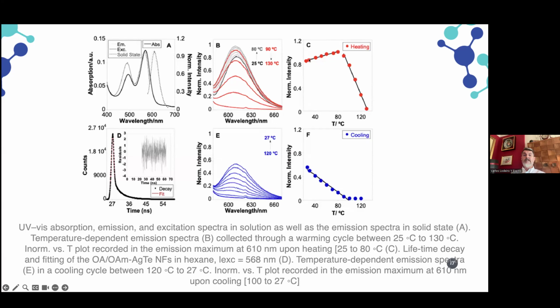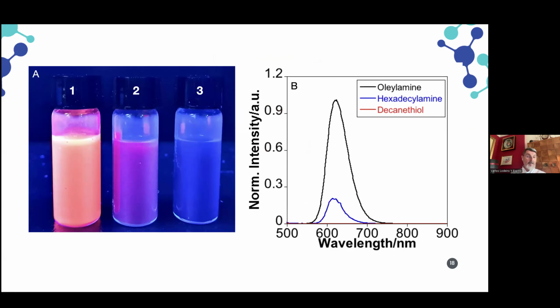We can modulate the temperature up to 100 degrees and the emission increases. This increased emission is because of the aggregation of the material, and then it is completely quenched after reaching around 150 degrees. The material is almost reversible. We can recover half of the intensity we started with, and the emission remains in the same position. Then how can we modulate this, how can we change it, with amines, for example.